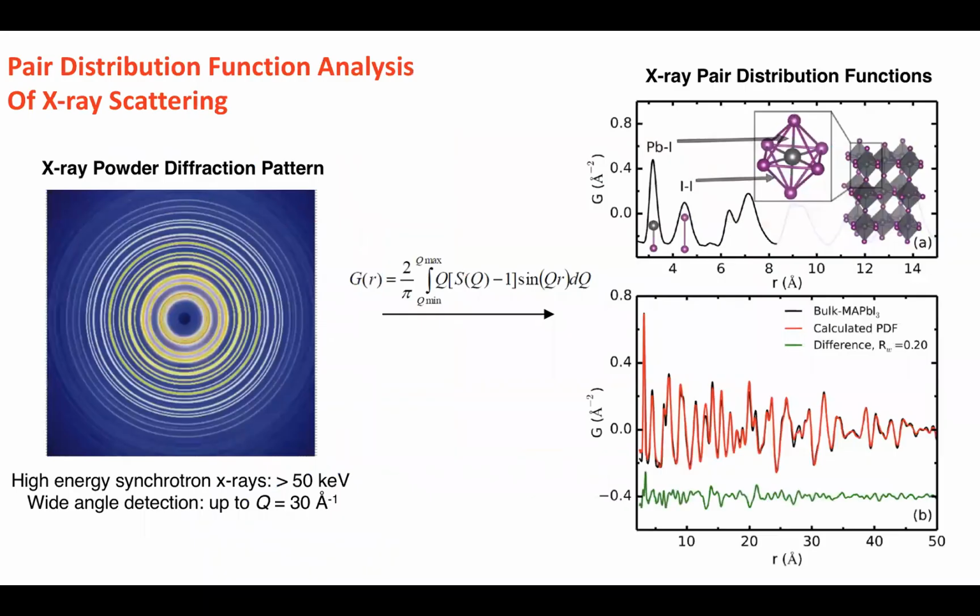So in this pattern, notice how the peak intensity decays, right? And peaks get broader, and that's because 5 nanometers away, there are no more regular correlations in the substance. And that tells you that crystallinity in this material is limited to 5 nanometers or less.